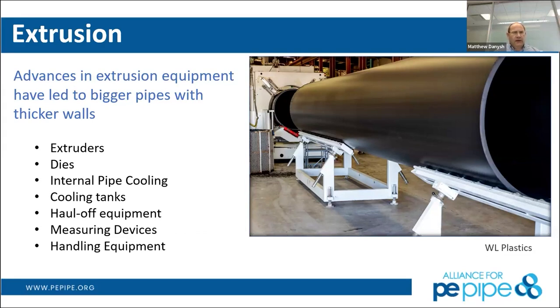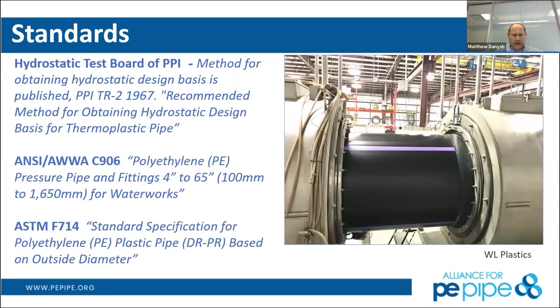And we've been making this large diameter pipe now for about 7 years. It's been on the market, and some of the standards have started to increase the sizes, like F714, which now goes up to 3 meters in diameter, which is 118 inches. So the specifications for F714 allow for these large diameters to be made under their standards. And the AWWA is still coming along with diameters up to 65 inches. So we're seeing the standards increase in their size range according to what can be produced in the industry now. And internationally, it is being produced as well. The ISO international standards are seeing sizes up to 3.5 meters in diameter.